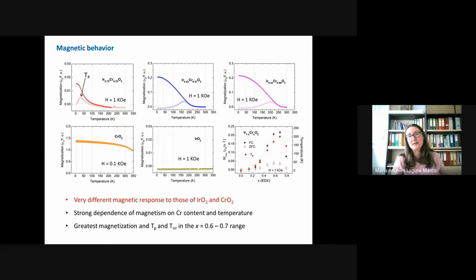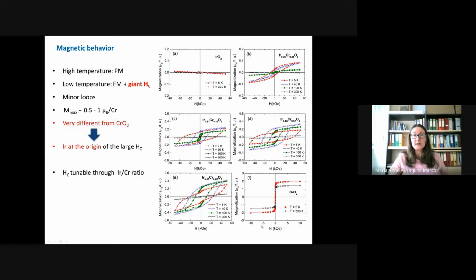And something similar happens to the magnetic ordering. It increases with the chromium content and reaches a maximum at about 0.6, 0.7 of chromium content. So at room temperature, all the films are paramagnetic, but at low temperature, the diluted films present a ferromagnetic component. As you can see in the hysteresis loops on the right, the diluted films present a high coercivity. For example, for about 60% of chromium content, the coercive field reaches 4 Tesla. And again, this is very different from the behavior observed in the pure chromium dioxide, as you can see in the right bottom panel.